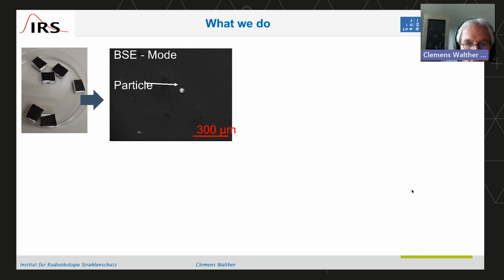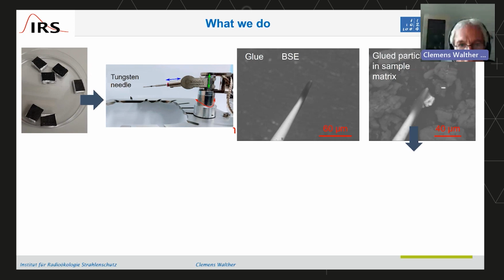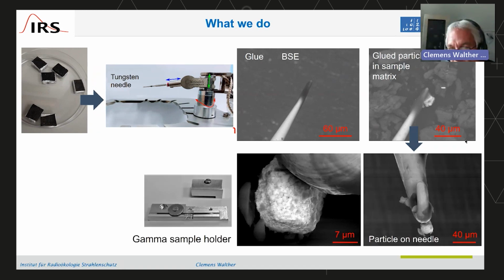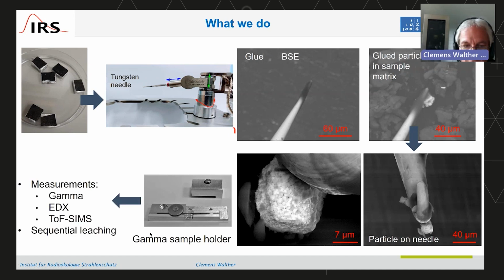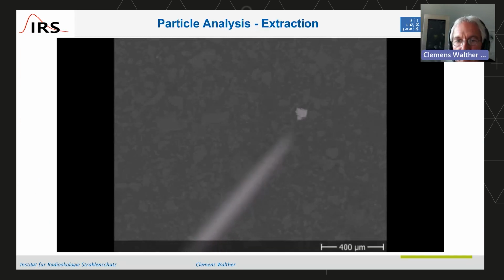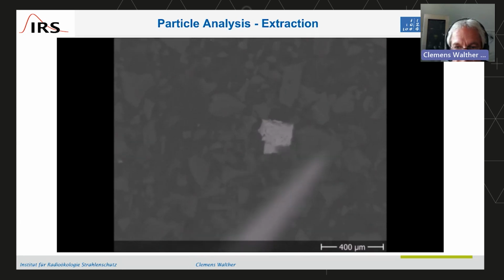Then we put those particles in the electron microscope in the backscattered electron mode, and everything that has a very high Z, a high atomic number, shows up bright. So you can see the particle here. Then we position that particle onto a very tiny tungsten needle and glue it with a special glue that hardens under the electron beam. Here you can see the tungsten needle and the particle attached to it. That is a macroscopic view. Imagine we have a tiny piece of nuclear material on here, and then we can do additional experiments like gamma spectroscopy, EDX or mass spectrometry, everything that I showed you in the beginning. So here is an animation. You see that particle under the electron microscope, and you have the tungsten needle. The tungsten needle attaches to the particle.